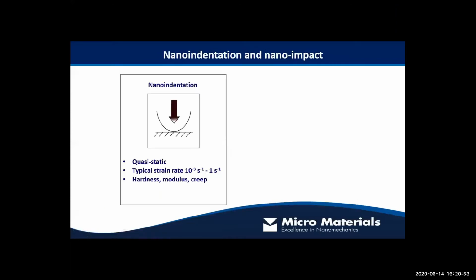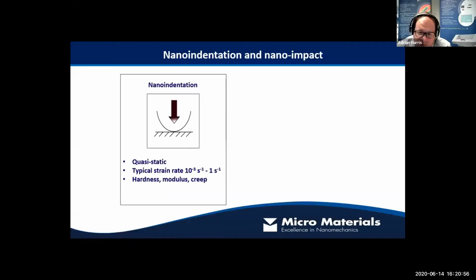Okay, I'll carry on. So, how does it work? Well, there are similarities to nano-indentation. Nano-indentation involves taking a probe and loading that probe normally into a sample surface. As we said, it's a quasi-static test, typically with maximum strain rates of 1 per second, the absolute highest really. And we measure hardness, modulus, creep, etc. So low strain rate properties. Critically, what we've done is we've brought the indenter to the surface very slowly and carefully, precisely detected the contact, and then performed an indentation test.